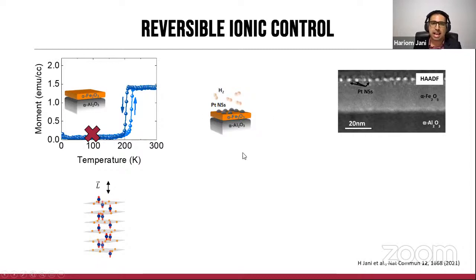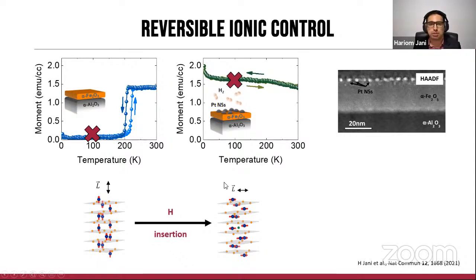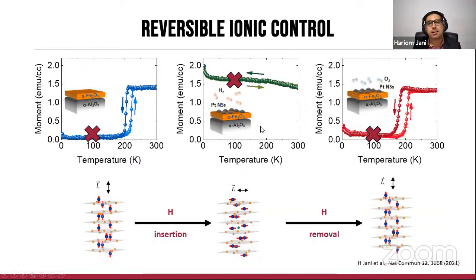So we actually have this hydrogen, which is then broken down into nascent individual atoms, and that enters the Fe2O3 to then fundamentally tune the properties. Firstly, by insertion of hydrogen, we completely suppress the Morin transition. So as you can see, this has the opposite effect of what rhodium does. And because hydrogen is a light ion, we can actually perform oxygen or argon annealing, and we can remove the hydrogen from the system, retrieve the original state and recreate the transition.